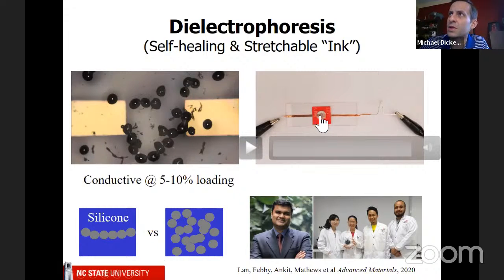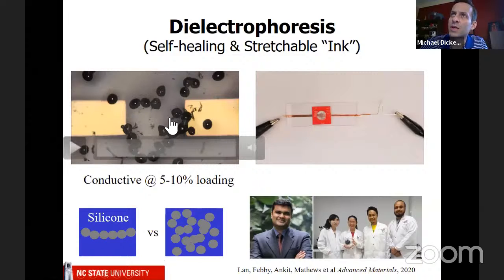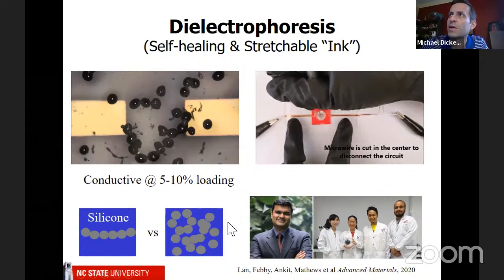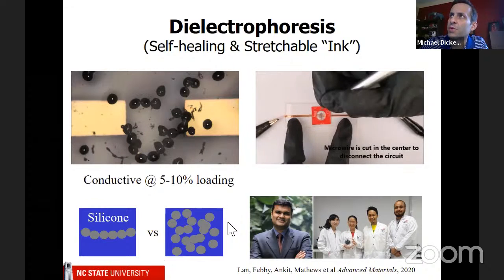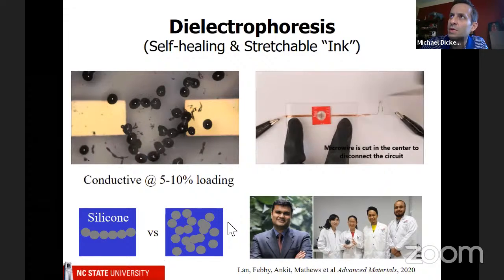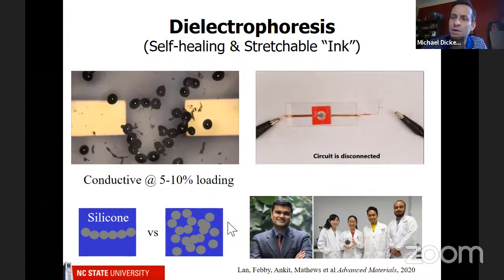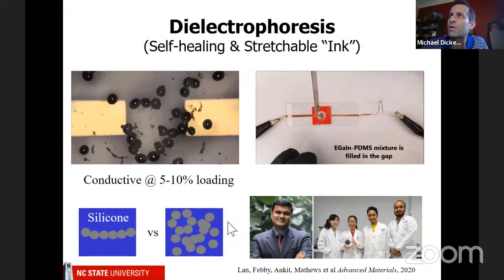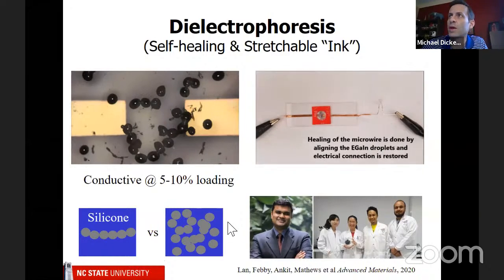As one example of a neat demonstration, this is a circuit that has two copper electrodes, and in the middle there's a gap, so it looks like this. The students are going to come in and cut it, and they're going to completely remove that material. They're going to pull it away with tweezers. So now there's no connection in this circuit. However, if you take this ink, which has the particles in it, it's still not conductive. But if you apply an electric field, you'll see that you can assemble the particles and restore the connection.